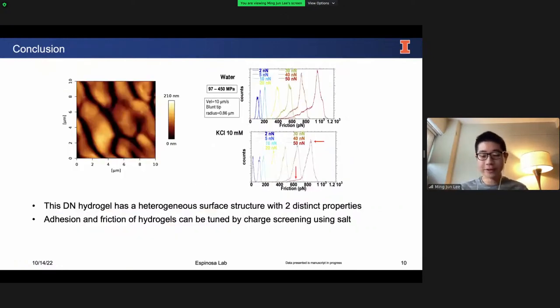To conclude my presentation, I want to remind you of two key components of this presentation. The first is that this particular system, agarose-poly acrylamide-co-acrylic acid, has a heterogeneous surface structure with two distinct phases of properties. And secondly, the adhesion and friction of hydrogels can be adjusted. We can control them by changing the concentration of the salt solution that we immerse them in over time. With that, I've come to the end of my presentation.